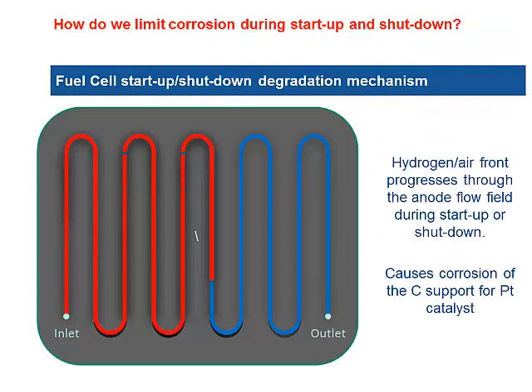One of the major issues with the current design is corrosion during startup and shutdown. That corrosion manifests as corrosion of the carbon — the platinum sits on the carbon, and if the carbon corrodes and converts to CO2 you lose that functionality. Startup is always a critical issue on any operating plant, whether a power plant, chemical plant, or fuel cell, because controlling the environment is the most challenging aspect. During startup, you have oxygen in the system because air gets into the fuel line, and as hydrogen goes through the system you get an interface that drives an electric potential causing corrosion.